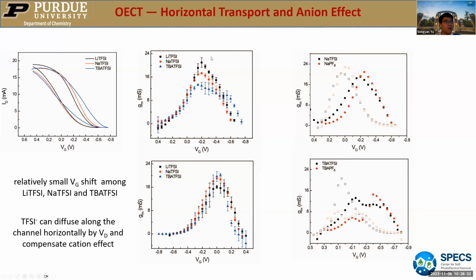But when we compare the ones with the same cation and different anion, we can see the one with TFSI shows an easier, lower gate voltage for de-doping, but a higher gate voltage for doping, and the separation between TBA TFSI and PF6 is even larger.